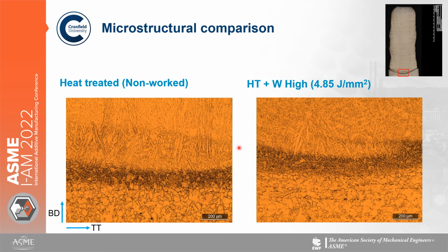And then again at the bottom, you can see our nice curvature of our remelt line on probably our first layer here, compared to our worked material, where we've got a nice indentation, as well as the disruption of the grains in the build direction. You can see it's much more orderly in our non-worked material.